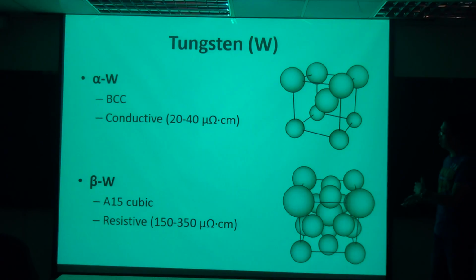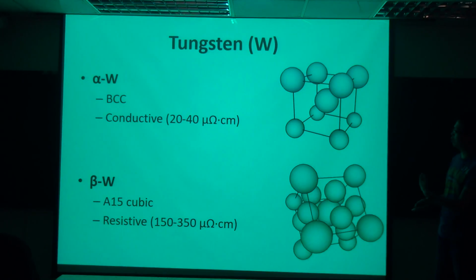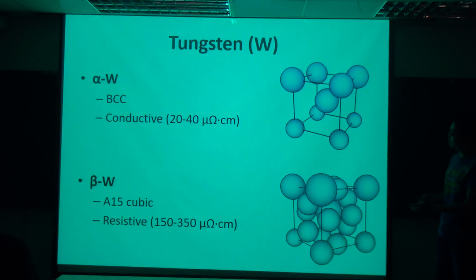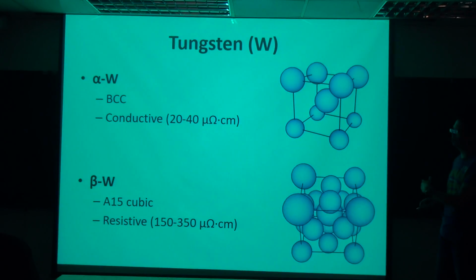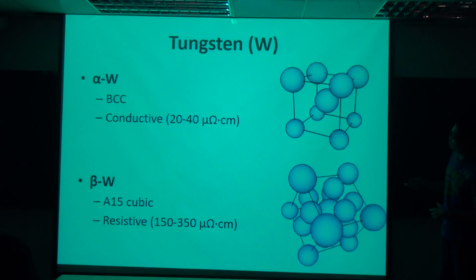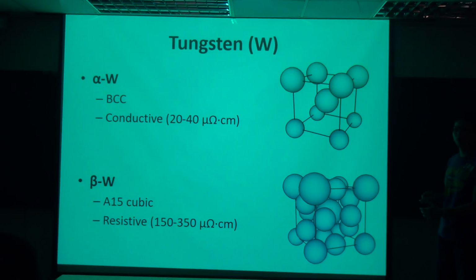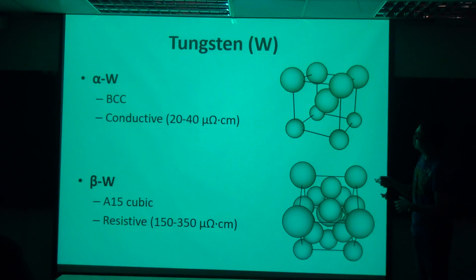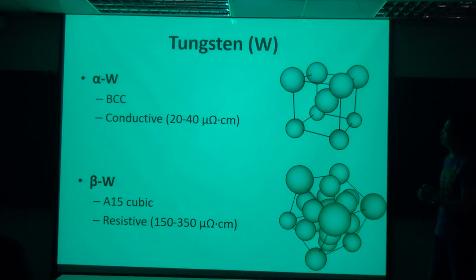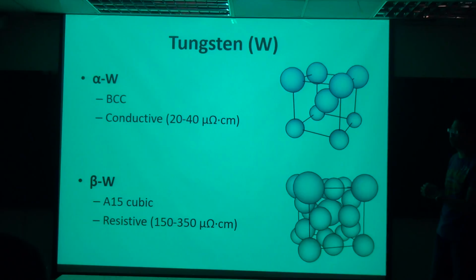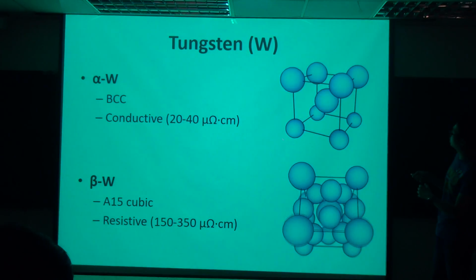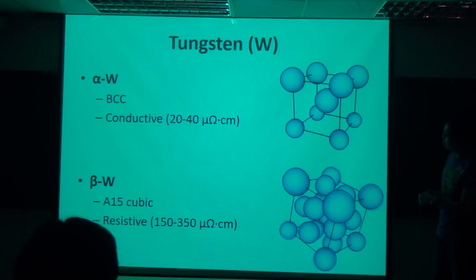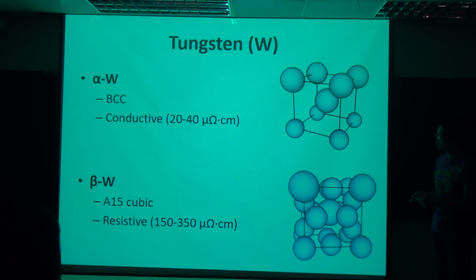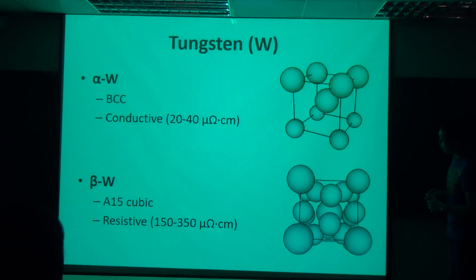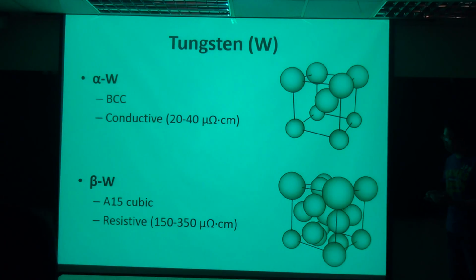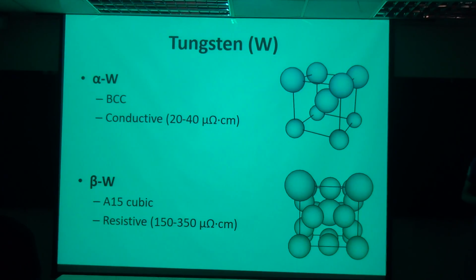But of course, that's not the story. At the beginning, I started from the tungsten, and I thought this was one phase, and then later I did some heat treatment, and I found that there's a huge change. So later I realized that there are two phases. And alpha tungsten could be really conductive. In the thin film form, this is almost close to the conductivity or the resistivity of copper. And typically it's in the BCC phase. And beta tungsten has an A15 cubic structure, and it's typically very resistive, around 150 to 350 micro-ohm centimeter.